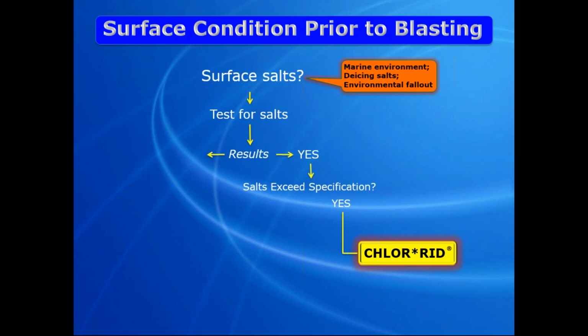The industry is allowing 5 to 7 micrograms per centimeter square or less for atmospheric zones. So if you do some testing, whether it's chloride, sulfates, or nitrates, and you find that these limits have not been met and you need to reduce the salt contaminants, you would just follow this pattern and use the Chlor*Rid product.